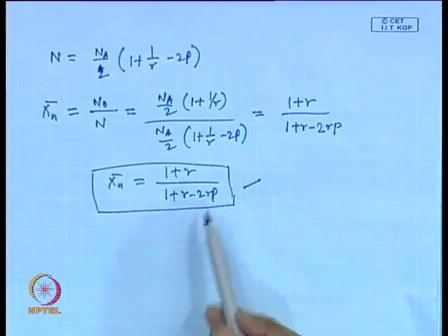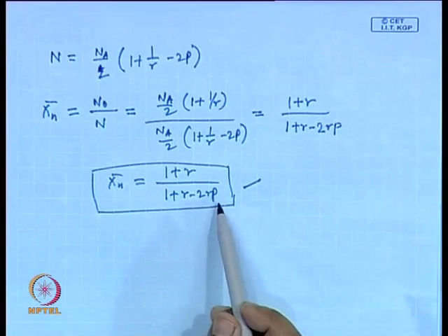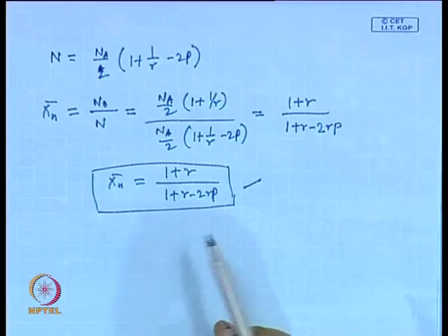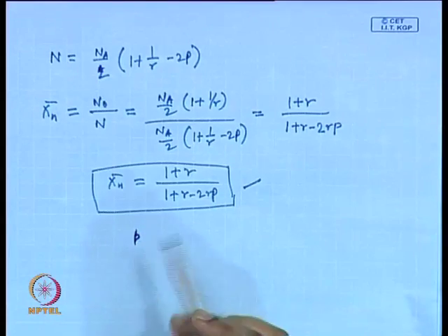Also, at the same time your reactor should be good enough that you can take out your condensate in an extreme way so that you can push your conversion up to P. Now, it is difficult to quantify P, because you cannot take out an aliquot during the reaction and determine the functional groups present, by which you could determine the conversion.